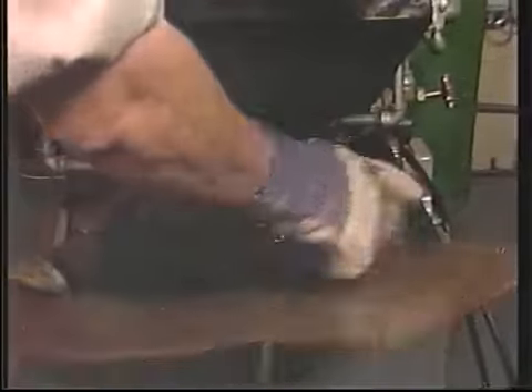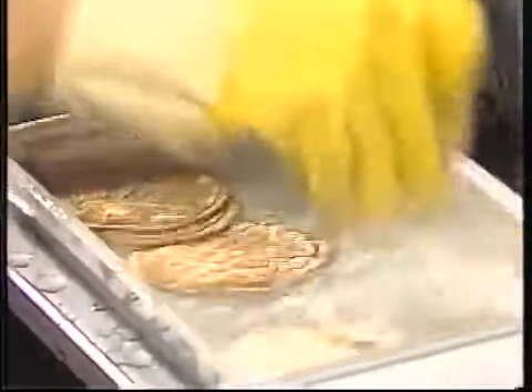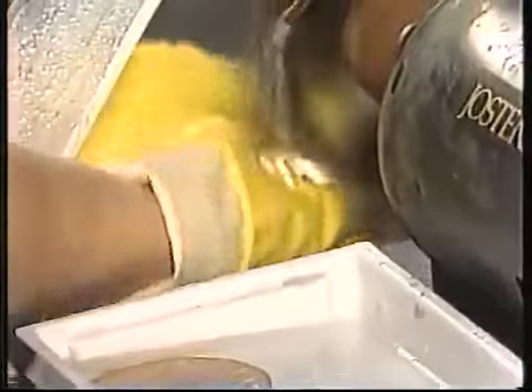During the annealing process, the pieces become slightly discolored as a result of the heat and the impurities on the surface of the metals. This is removed by bright dipping the piece in an acid solution to loosen the residue. The residue is then removed under a brass scratch brush with cleaning solution running on the scratch brush and flushing the material off the piece.